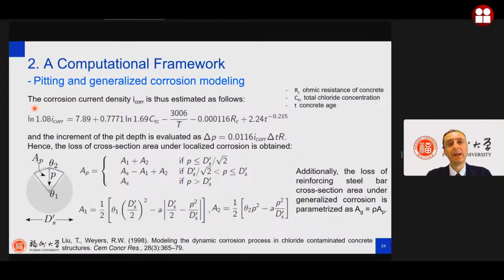And after, in this way, we can estimate the corrosion current density. This is a law that is more than 20 years old. We are also trying to develop a new law based more on data analysis, but the very big problem is that actually there is not so much data to be used. So we need more data. And we consider the generalized corrosion, but also the pitting corrosion. And this is how we approximate the effect of the corrosion.